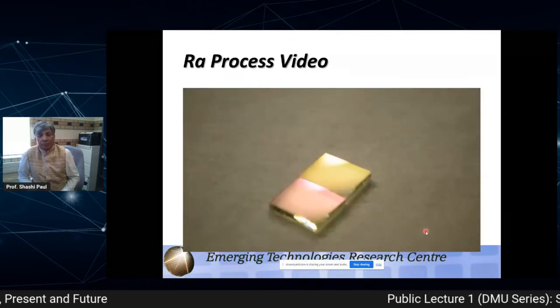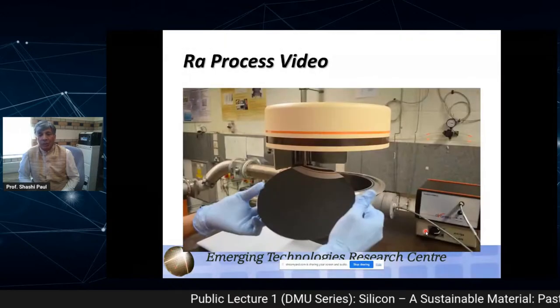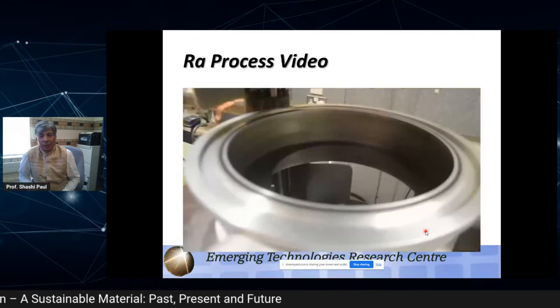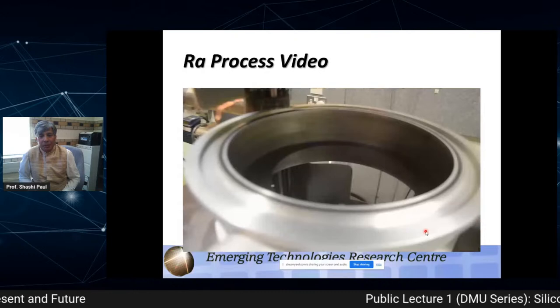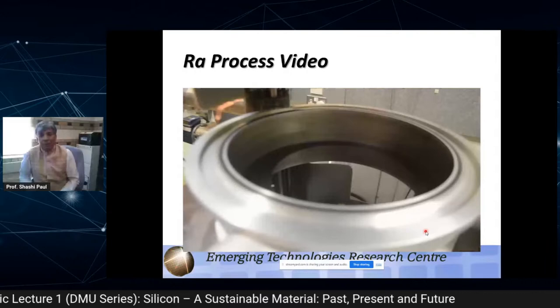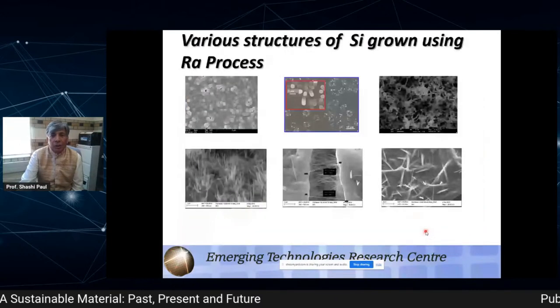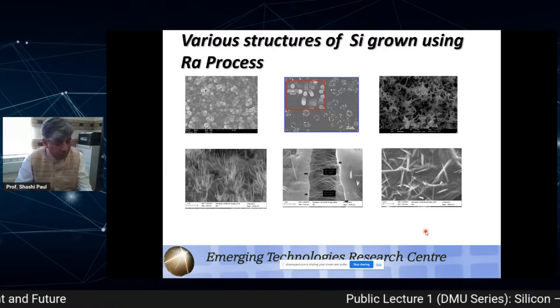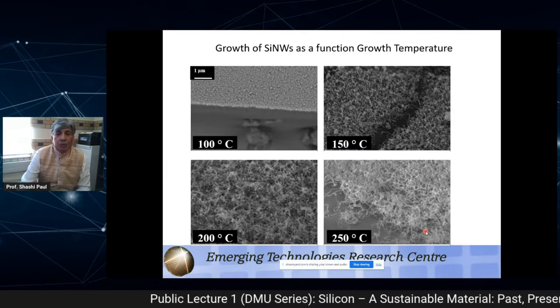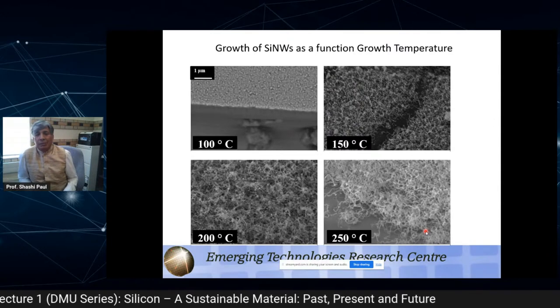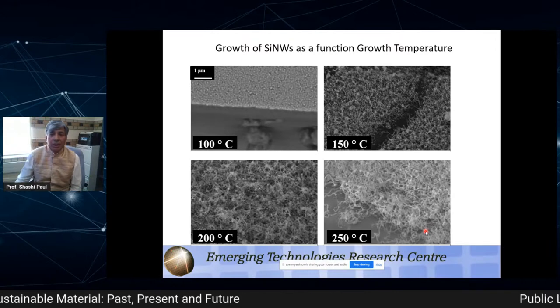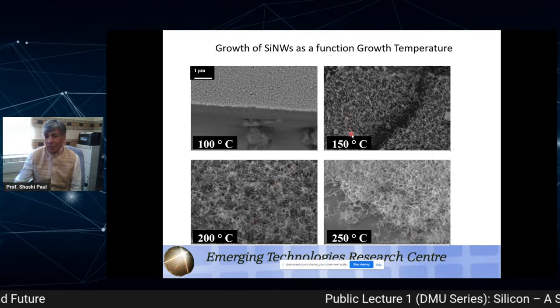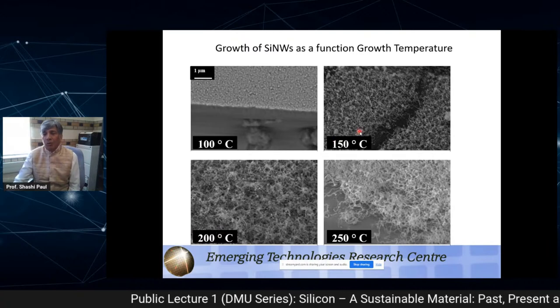Once you've done that, you can take it to PECVD, where we grow these wonderful silicon structures. It can take up to a 10 inch wafer. Okay, so again, I think I need to rush through. The lowest temperature we got with this technique, by which we can grow these crystalline silicon structures, is around 200 degrees centigrade. We can lower the temperature below 200 degrees centigrade, but unfortunately a lot of amorphous silicon is there.